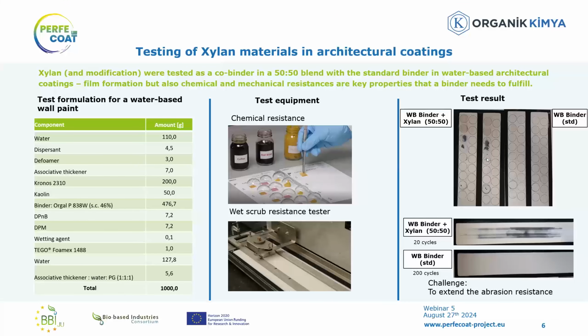Then I'm going to switch to my last set of data. This was generated by our partner, Organik Kimya. So I'm presenting on behalf of Erin Elek, who presented in earlier webinars together with me. Here we have tested the xylan and modified xylan that was introduced by Brian earlier. They were tested as co-binders in the water-based wall paint that you can see. They were used 50% in mix with a standard binder, the Orgal from Organik Kimya, an acrylic emulsion. We looked at first the film formation, the appearance of the film, and also the main key performance in terms of chemical resistance and wet scrub resistance, again, as described earlier.